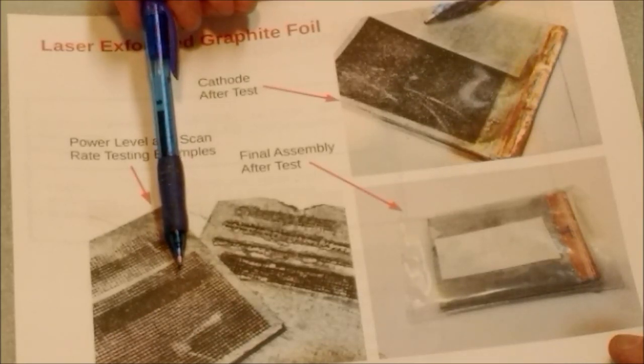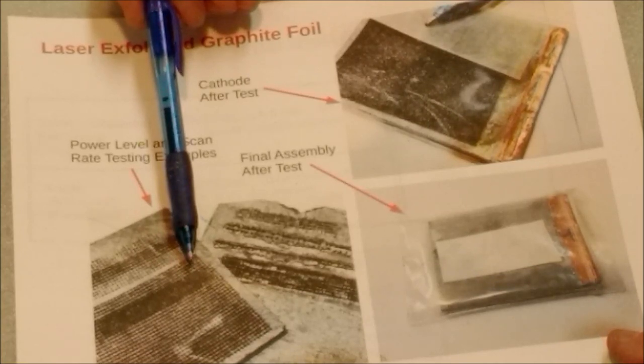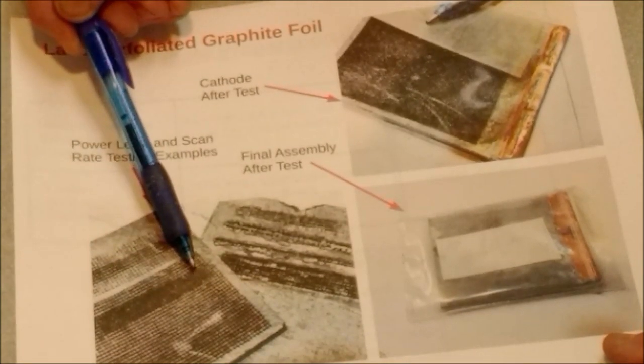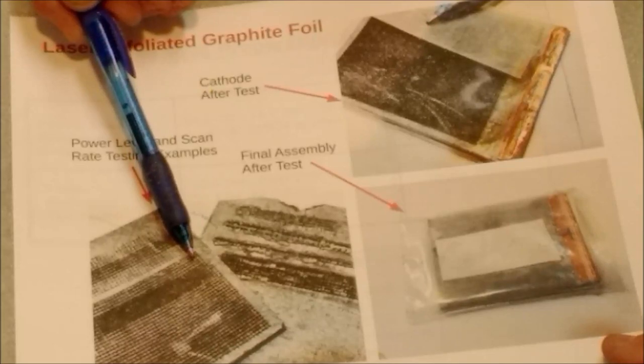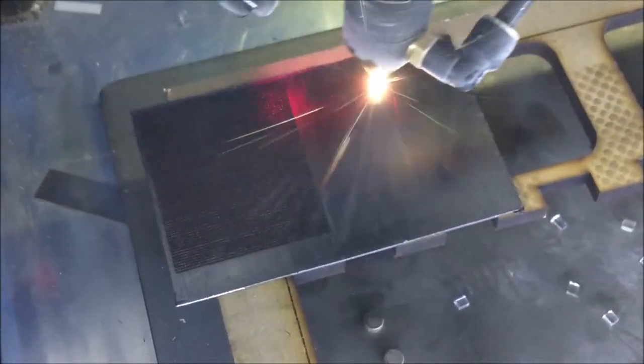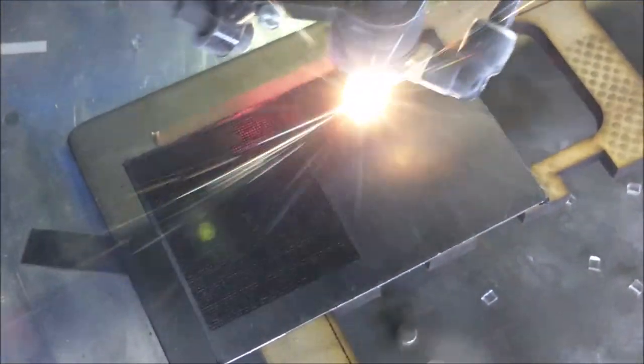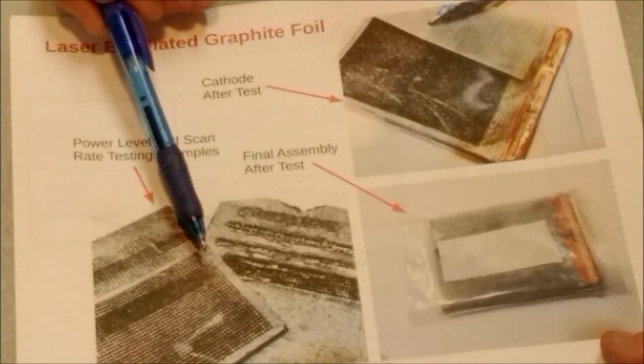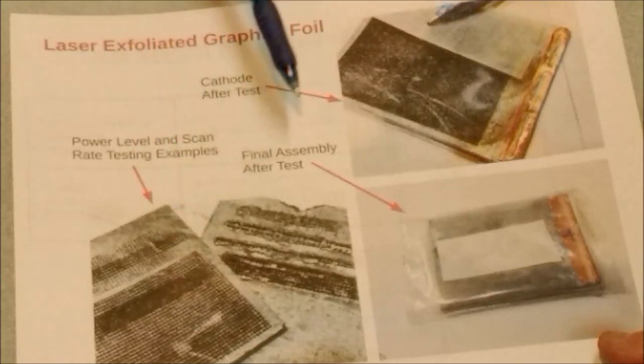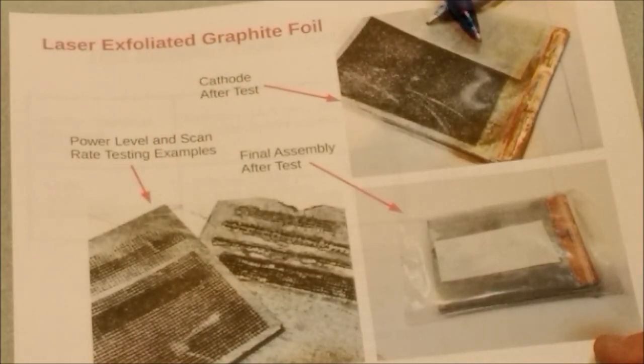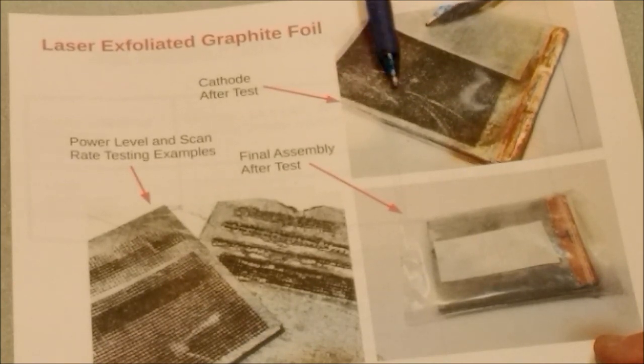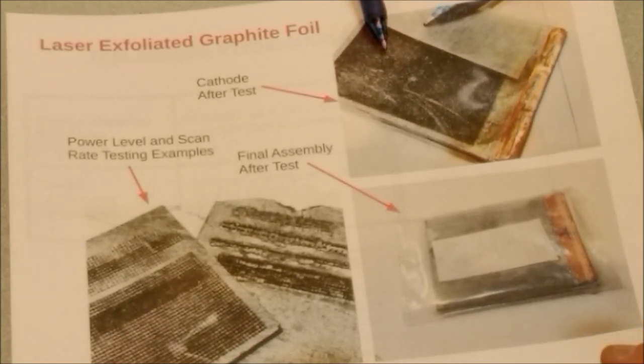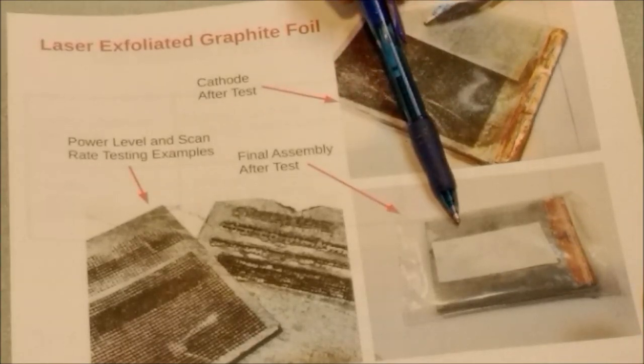I guess you could also argue that the carbon is heat treated at that point, but somewhat in an uncontrolled fashion. From the little video clip of the laser scanning, it's an extremely bright light once the laser, which is infrared, hits the carbon. It's basically a carbon arc light at that moment, so I'm sure we're well into the 1-2000 degree temperature range as we heat up the carbons with the laser. And then over here with the cloth pulled back, you can see the compressed pattern that still remains on the surface. This was after the testing.